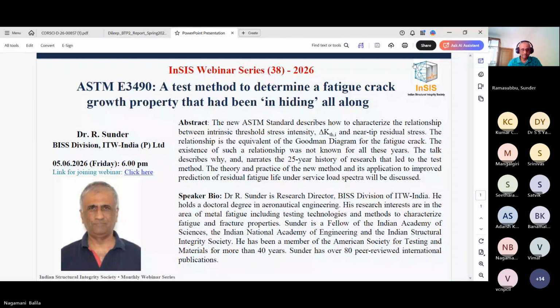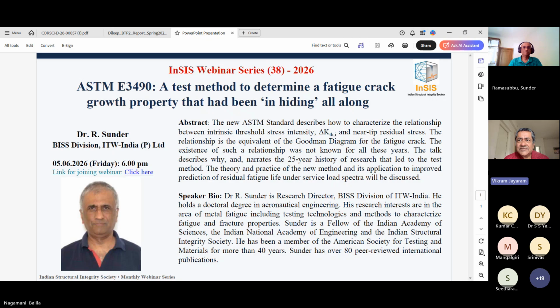For those of you who work in fracture mechanics, we know about fatigue threshold, the fatigue limit in smooth samples and notch samples, and we also know that it depends on mean stress. Dr. Sunder has, I think, for the last 20 years, been arguing that a similar argument should apply for the case of ΔK, that is the fatigue stress intensity factor amplitude threshold. And this is the story of that exercise.